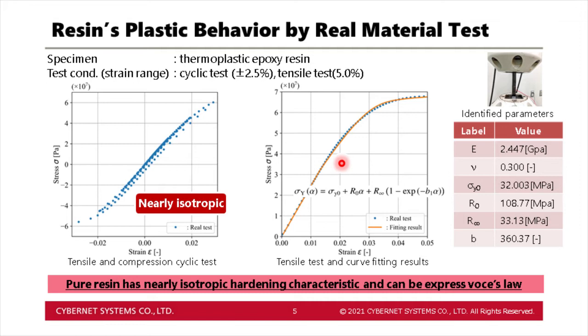In the cyclic test, we were not able to test to the large strain range due to buckling in the compression side. Therefore, a separate tensile-only test was conducted exclusively for the identification of the material constants. For the isotropic elastoplastic material model, we used the Voce law as shown here. It was confirmed that it can be fitted very well.